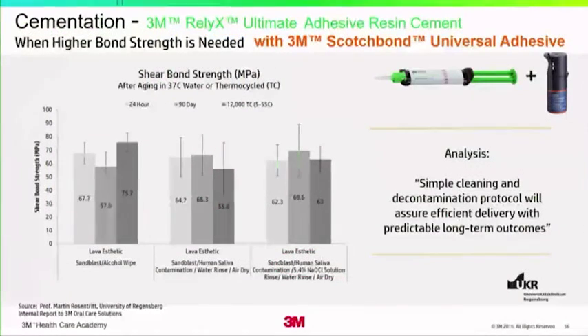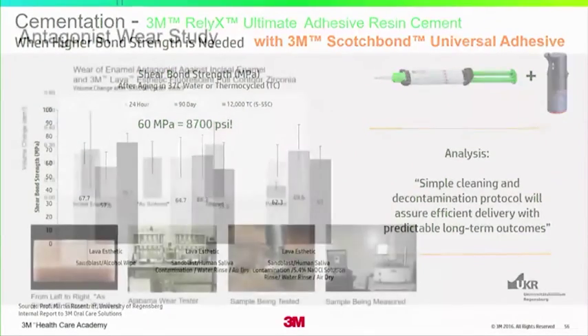If you need a higher level of bond, you're going to use a high-performance system, and of course this would involve a separate adhesive primer. Scotchbond Universal, which I call a universal primer, can be used in conjunction with the RelyX Ultimate cement to get a very efficient and stable bond to the material. And again, at quite a bit higher level, rather, from the Unicem 2.